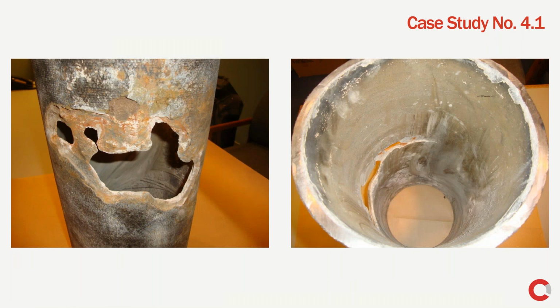What caused the corrosion in this particular case was the presence of an old railway track in close vicinity. So there was a flow of current between the railway track and this pipe. What is typical for stray current corrosion is the fact that it's very localized and the pipe is not affected inside. You can see on the left image the typical appearance of an underground pipe which is affected by stray current corrosion, and on the right side image you will see the interior of the same pipe which is basically not affected.